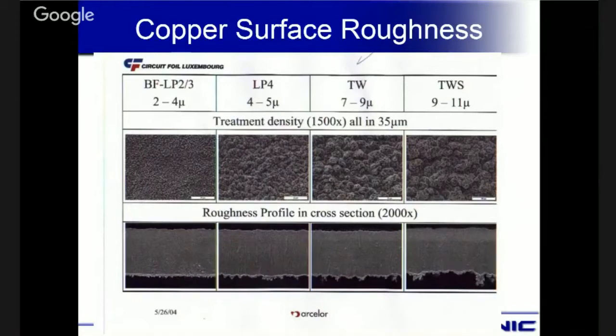The issue with 2-ounce copper on the boards, because you want higher power level, is that they're very, very rough. And so I always say, we've got a problem here, because in order to get the lower loss, higher RF power dissipation on your boards, you really want smooth copper. And 2-ounce copper does not come smooth. It's very, very rough. So I always try to convince people in the broadcast industry they should actually buy the smoother 1-ounce copper, and then have the board shop plate the copper up to the required thickness, rather than buying the thick copper from us.